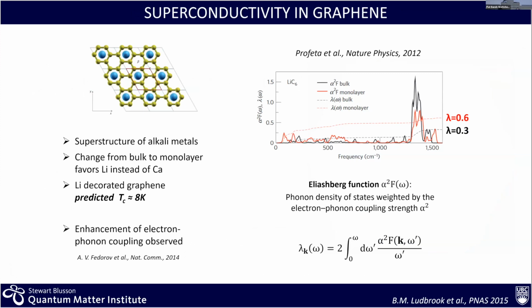I like to start from superconductivity. This is the first thing we did. In this case, we followed a proposal by an Italian group, Profeta in particular, and collaborators, who look at the idea of having graphene, whether freestanding or on silicon carbide, and then grow a superstructure of lithium atoms on top of it, and use that to modify the electron phonon coupling in the system and induce superconductivity.